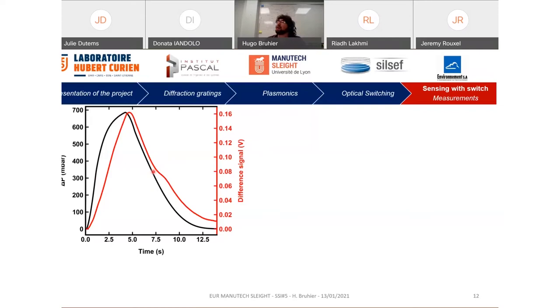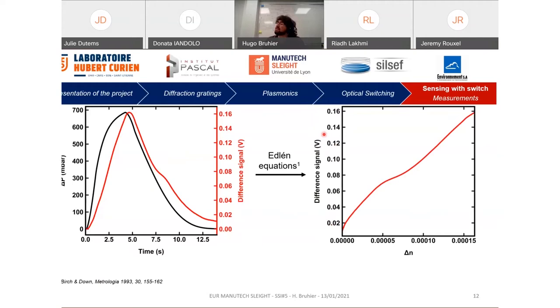But here it's just the difference of pressure measurements, and with Edlén equations we can have a relation between the pressure measurements and the refractive index, and so we can plot this, which is the difference signal versus the change of refractive index. And between two times, which is nearly 6 seconds and 2.5 seconds, we plot this curve